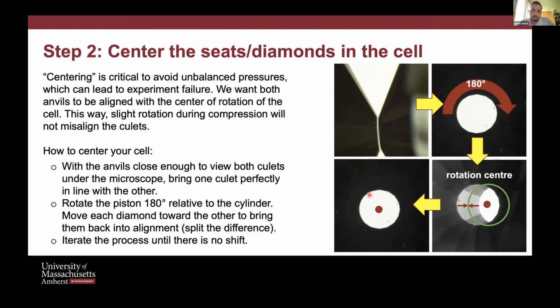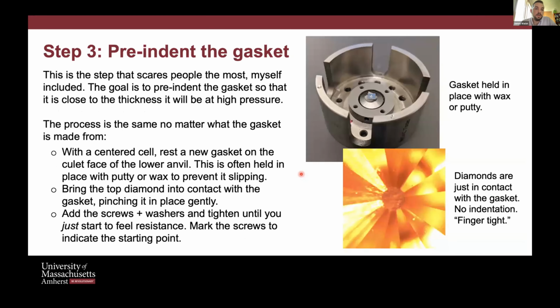So this is the routine that you should get used to. Only when you can rotate one of the anvils relative to the other, or really the whole half of the cell relative to the other, and you don't see misalignment. That's the case that you want to get to, that you see fully eclipsed, even when you do a 180-degree rotation. Yeah, so then you would iterate the process. You may not always get it right the first time. I usually have to go a couple of times and go back to the original rotation until I see absolutely no shift. So that's centering the cell.